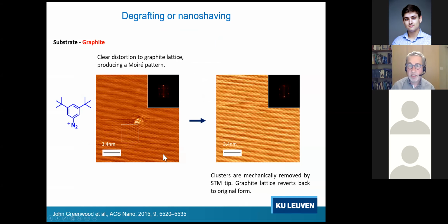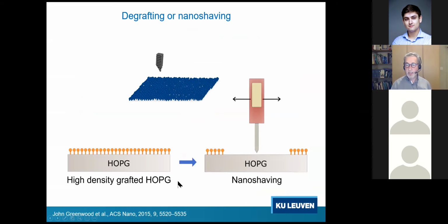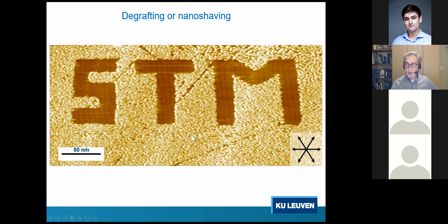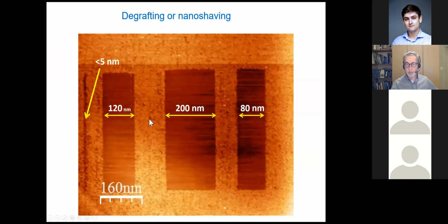So let me now quickly go to the combination where we use nanolithography. For the nanolithography, the top-down approach, what we do is the following. We have already our chemically modified surface, so these aryl radicals have covalently formed a bond with the substrate. But we can use the STM tip to locally remove them by bringing the STM tip closer to the substrate. And we can start to write. All these bright dots here are molecules covalently linked to the substrate, and these letters are areas where we have removed these covalently grafted molecules using the STM tip. You can create areas of a given size and shape. We have full control on that.